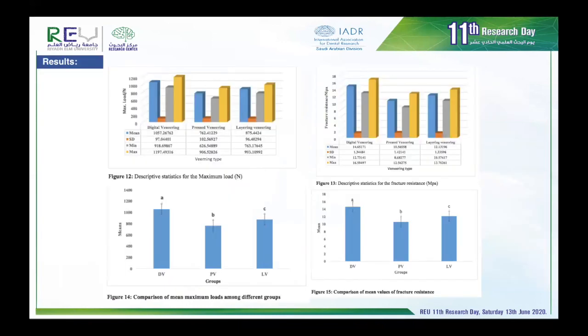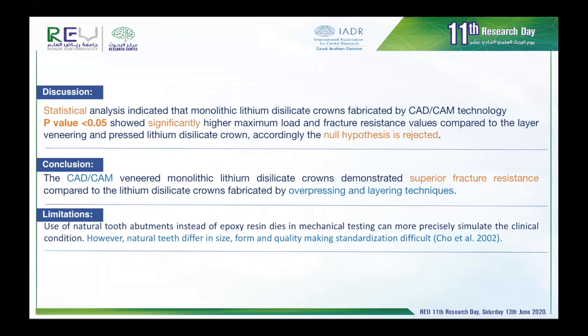The results of our study showed clearly that the CAD/CAM group provided the greatest value of fracture resistance, followed by the layering group, and the least fracture resistance values were recorded for the pressed veneering technique group. The statistical analysis showed a significant result where the p-value was less than 0.05, and we concluded from that the CAD/CAM veneered monolithic lithium disilicate crowns demonstrated superior fracture resistance values as compared to the other groups.